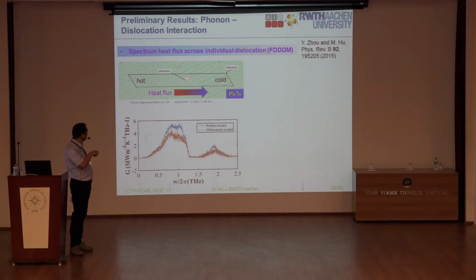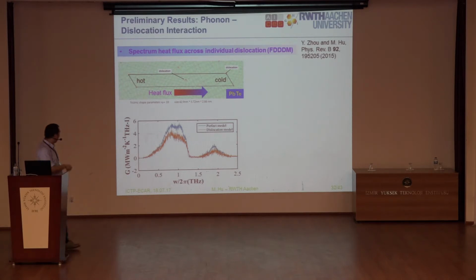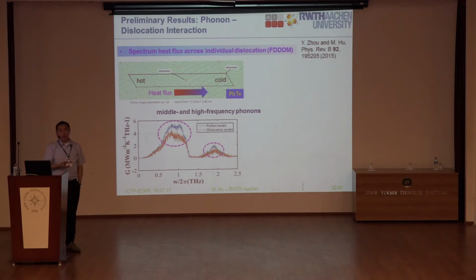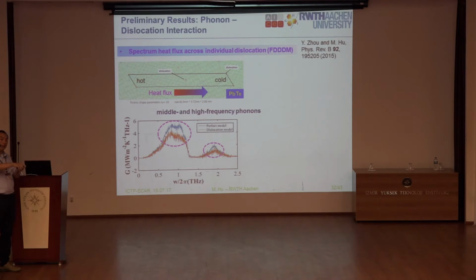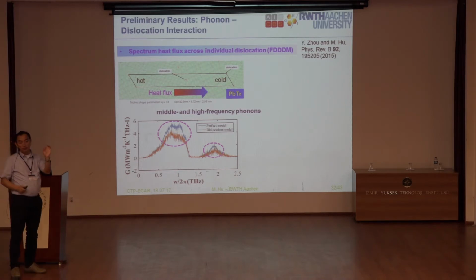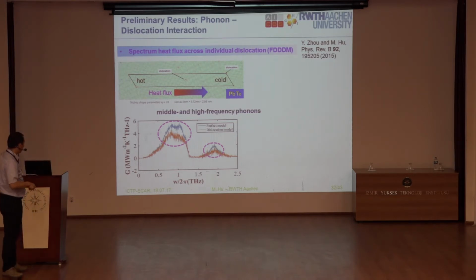So now we just introduce a single isolated dislocation inside the material, and then we keep a hot part, cold part, and then there's a heat flux, right? And then by decomposing the heat flux into different frequencies, we found that the middle and high frequency phonons are affected, right? It goes down, but the low frequency phonons are not affected. So this is somehow expected because low frequency phonons normally have long mean free paths, and the isolated dislocation in this case is something like a big point defect. And then the phonons with long mean free paths just pass away, right? So the same phenomenon is also found by the equilibrium MD.